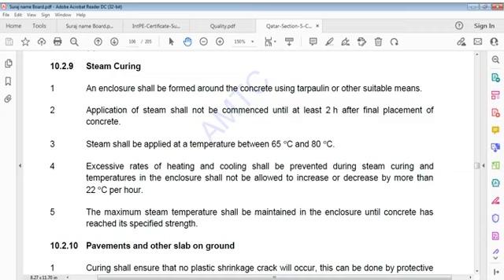So we have to keep in mind variation of 22 degree maximum, and steam working temperature should be 65 to 80 degrees Celsius, and we have to wait for 2 hours after concrete placement to commence with steam application. And we have to arrange one enclosure, that's tarpaulin or other suitable means which does not allow release of steam. So maximum steam temperature shall be maintained in enclosure until concrete has reached its specified strength.